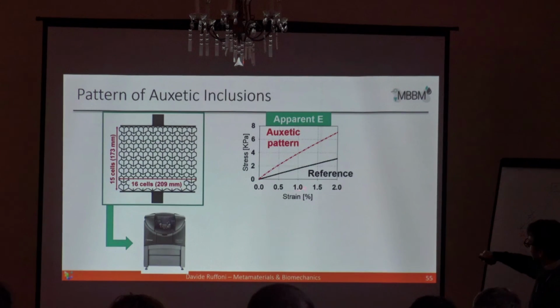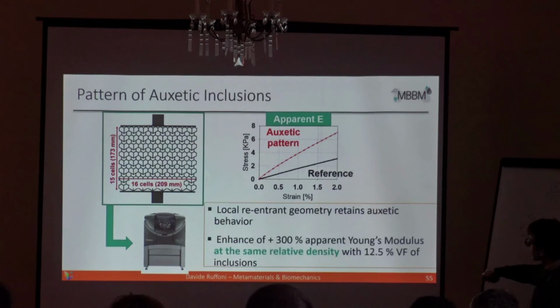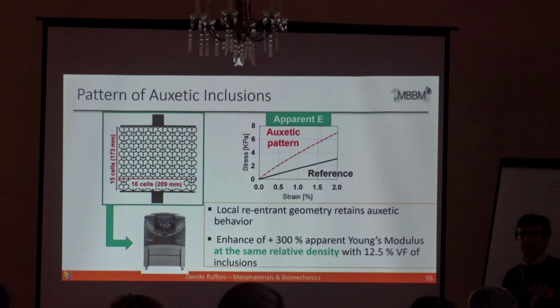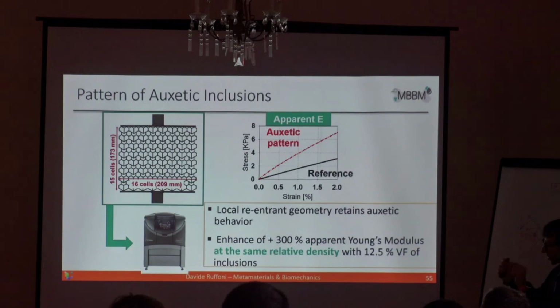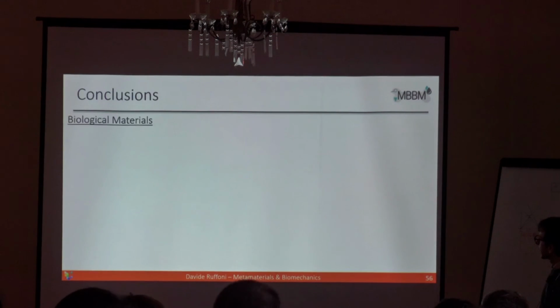We see that with respect to a positive Poisson ratio lattice, by inserting this auxetic pattern, we have an increase in stiffness of 300%. And I stress this is exactly at the same relative density. So I'm not adding more material here. This is exactly the same material, but just by exploiting this contrast in Poisson ratio, we can increase the overall stiffness of the lattice. And that's basically it.